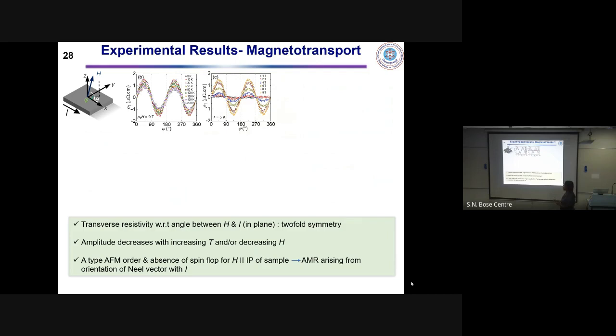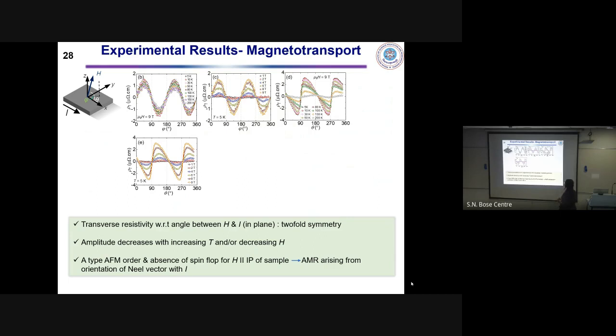Now, considering that it has A-type antiferromagnetic order below T_N, about 1.25 K, and absence of any spin flop configuration for H in the plane of the sample, this can be attributed to simple anisotropic magnetoresistance behavior arising from the orientation of the Néel vector with respect to the current, which is common in magnetic materials. However, what was striking is what we saw when we measured the transverse resistivity as a function of theta.